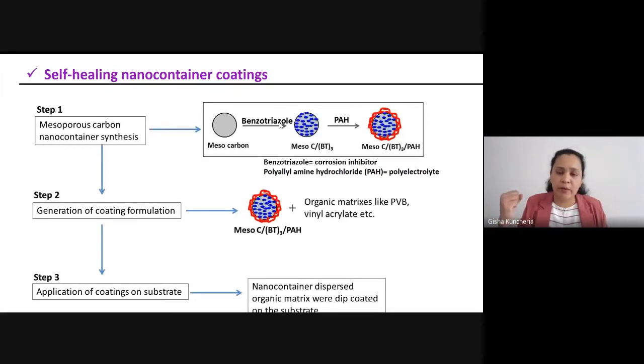So by giving the vacuum, we remove the air trapped inside the pores of the mesoporous carbon, and the pores are filled now with benzotriazole. So the pores are now covered. We have to cover it, close it. So we close the pores with a polyelectrolyte, polyallylamine hydrochloride. So this is the nano container. So this container is mixed with a polymer coating. For the polymer coating, we used vinyl acrylate.